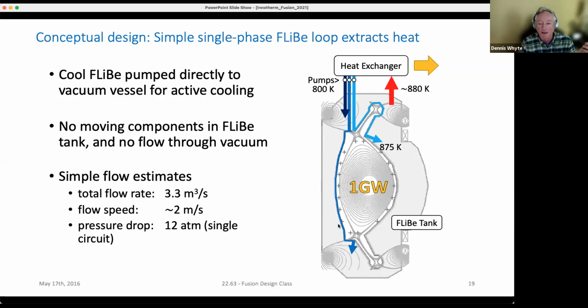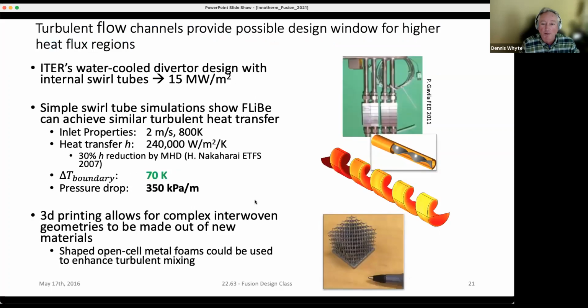You get forced convective flow through this. Very nice, a simplification actually, it just empties out into this big volume of the liquid, and then you recover this liquid back out into the hot part of the heat exchanger. This is, of course, driving your turbines and so forth. Here we did some simple estimates of things like the total flow rates. A few cubic meters per second is enough to establish thermal equilibrium, the entirety of it has a reasonable flow speed, and you can see it's a few atmospheres of pressure drop.